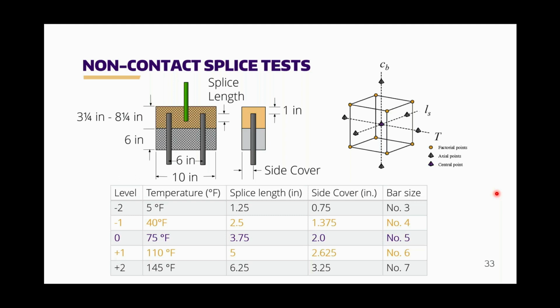And just to break down what this specimen looked like a little bit more, we had 2 number 8 bars, just standard rebar, and that was embedded in 6 inches of cementitious concrete. And then those number 8s stuck into the HCSC. That's the gold section in that figure. And that's where the splice occurred between our epoxy bar and our standard number 8s within that HCSC.